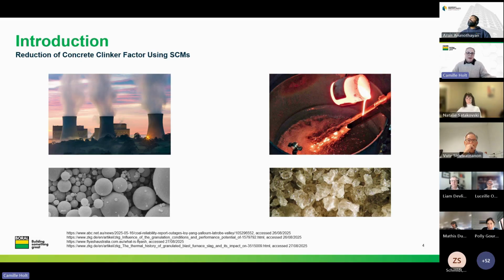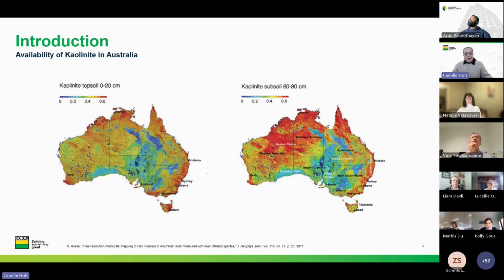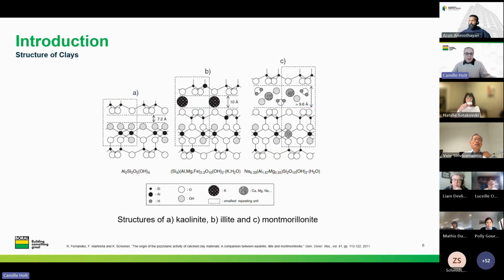And so this is why we're here today talking about calcined clay. It's widely available. It has been well studied in the literature and is proving itself a viable supplement to our current SCMs. And there are significant amounts of kaolinite in Australia, as indicated by the map on the slide, with deposits close to major cities. And so this can minimise the distance that the clay would need to be transported, which is important for cost as well as carbon footprint. And so kaolinite is the clay that we normally tend to talk about, but there are other types of clays.